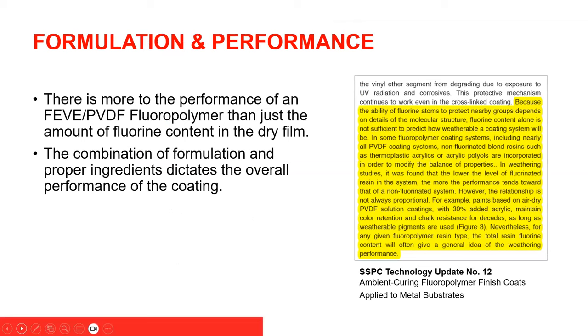So as Mark has discussed with regards to formulation and performance, there is more to performance of the FEVE or PVDF fluoropolymers than just the amount of fluorine content in the dry film. So you might hear, I need a fluoropolymer coating that has 70% fluorine and 30% PVDF. It's really more about the combination of the formulation and the proper ingredients that dictates the overall performance of the coating. And we're just showing an SSPC technology update that reiterates that fact.